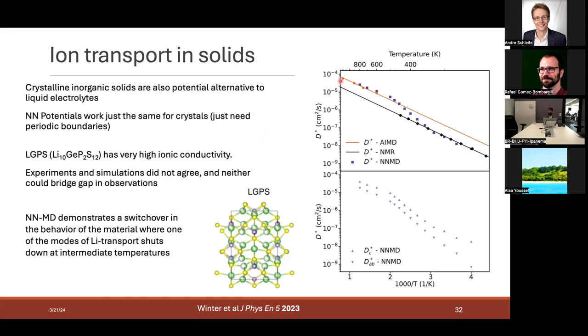And interestingly, it had been simulated by folks that had to pay full price quantum mechanics. And because they were paying full price quantum mechanics, they could only simulate for like 5-10 picoseconds, right? This was already a big price. And in 5 picoseconds, the only way you can measure the diffusivity of lithium in this material is by running the simulations very, very hot. So these folks in the red points here, they simulated the material at 800 Kelvin, which is way higher than you can actually measure it, but they were able to simulate it paying full quantum mechanics price.